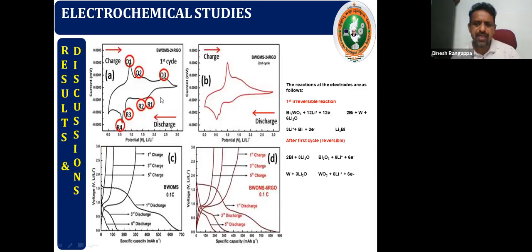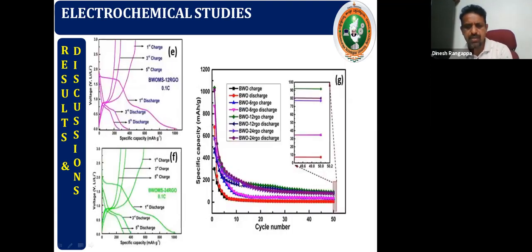So here you can see pure bismuth vanadate shows capacity up to 700, and with RGO we can see increased capacity. So this shows the bismuth vanadate formed under the supercritical fluid process is also electrochemically active compared to the pure material, and along with increased RGO concentration, the capacity was further increased.